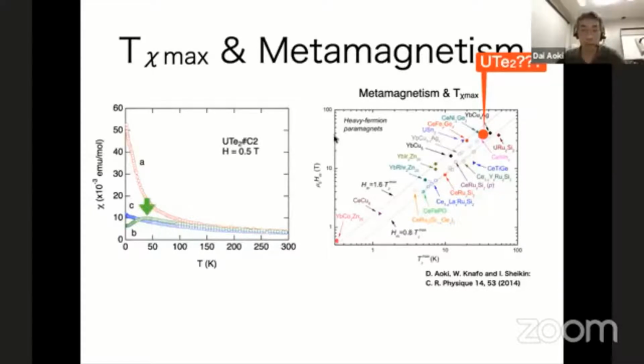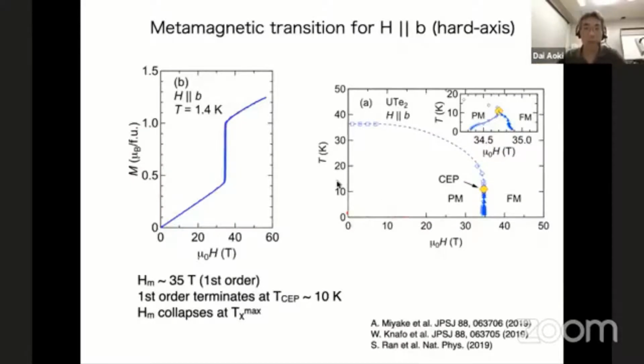And indeed, it shows a very sharp metamagnetic transition. This magnetization measurement was done by Atsushi Miyake, and Shen Ran also reported a similar metamagnetic transition. You can see here at 35 Tesla a sharp metamagnetic transition, and it shows a hysteresis. So this is indeed a first order transition. If you draw the phase diagram, T chi max is connected to the metamagnetic transition like this. Because this is a first order transition, it can terminate and change to a crossover. This point we call the critical end point, and this line is the crossover connecting to T chi max.